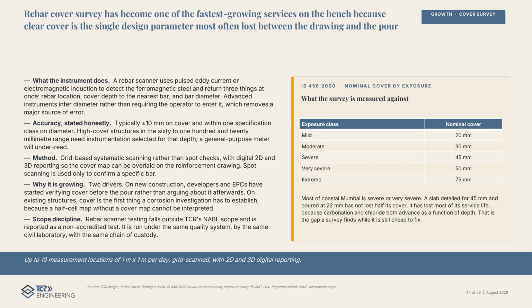Rebar cover survey has become one of the fastest growing services on the bench, because clear cover is the single design parameter most often lost between the drawing and the pour. The scanner uses pulsed eddy current or electromagnetic induction to return rebar location, cover depth, and bar diameter together, typically within 10 millimeters on cover. We scan on a grid, not on spots, and report in 2 and 3 dimensions, so the cover map overlays the reinforcement drawing. Most of coastal Mumbai is severe or very severe exposure, needing 45 to 50 millimeters. A slab poured at 22 has not lost half its cover. It has lost most of its service life.